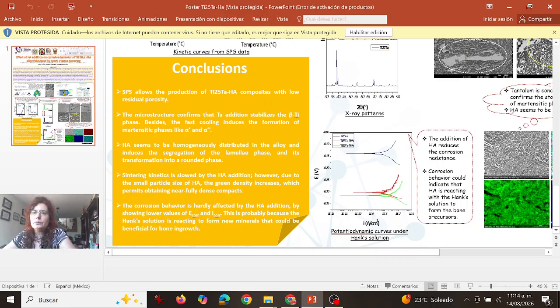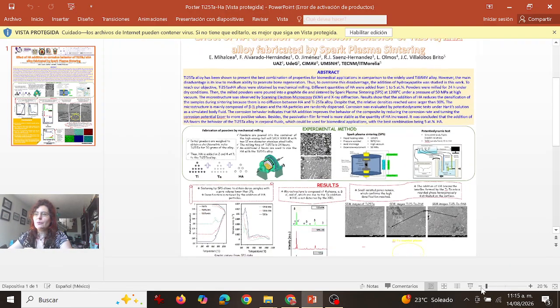The sintering kinetic is slowed by the hydroxyapatite addition, but however, due to the small particle size of the hydroxyapatite, the green density increases, which permits obtaining near fully dense compacts. And the last conclusion was that the corrosion behavior is affected by the hydroxyapatite addition, showing lower values of Ecorr. And this is probably because the Hanks solution is reacting to form new minerals that could be beneficial for the bone ingrowth. All right, that's all for my presentation.